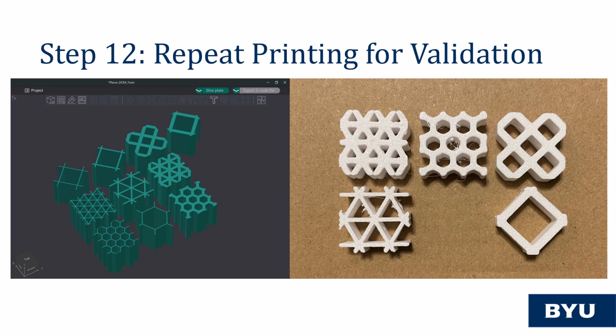Next, a second design of experiments was generated across the original design space to validate the model. In this case, 10 models were generated to fill the design space. However, like before, the samples with the thinnest lattice thickness were failing to be printed. In the end, only 6 of the 10 designs finished printing. The image on the right shows 5 of the 10 designs from one of the repeat print attempts.